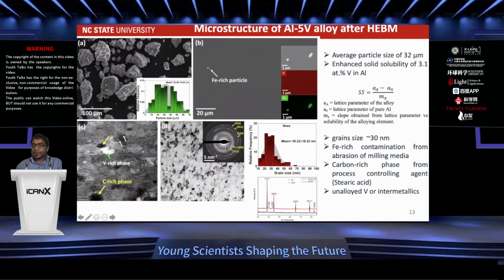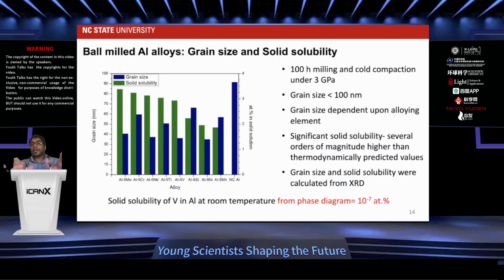I guess I won't talk about all those individual details, but if we summarize the microstructure, we get a really heterogeneous microstructure, right? If you look at the grain size, that's really just tens of nanometers, 10, 20, 30 nanometers, definitely stays below 30 nanometers. And depending on the alloying element, we can get different solubilities.